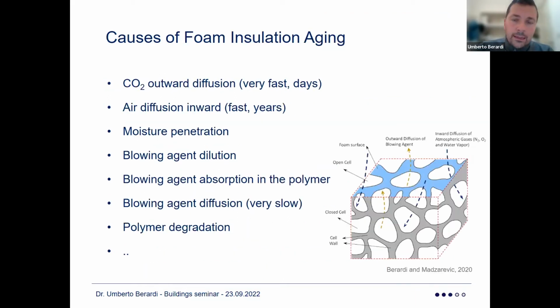So the reality is that these kind of gases are much more environmentally friendly. But on the other side, they have a bit of challenges, and we've been working on improving the challenges of these gases. Number one, the CO2 tends to escape from the material, and so air diffuses inside the material. And with air, a lot of water vapor enters into the material. So moisture penetration is a problem.